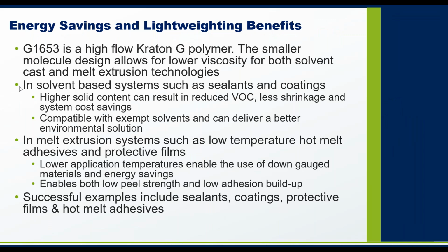So the key message for G1653 is that it is a high flow Kraton G polymer and is a smaller molecule than many of the other classic G grades like G1657. Commercial successes have been achieved in both solvent and melt extrusion systems. In the solvent-based systems, such as sealants and coatings, a higher solid content can result in reduced VOC, also less shrinkage and potential system cost savings.